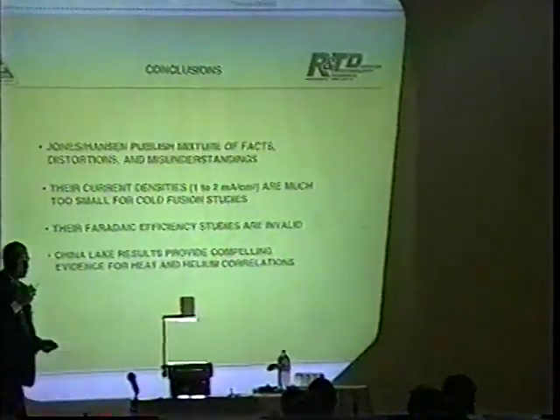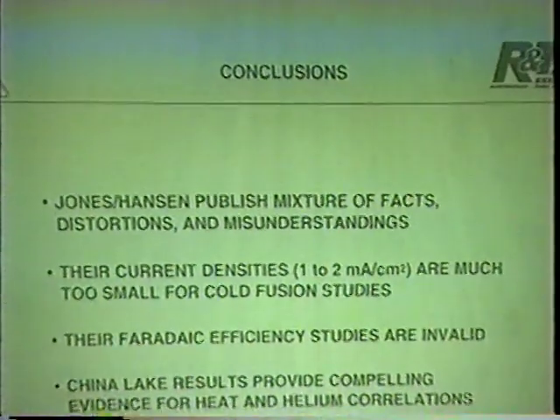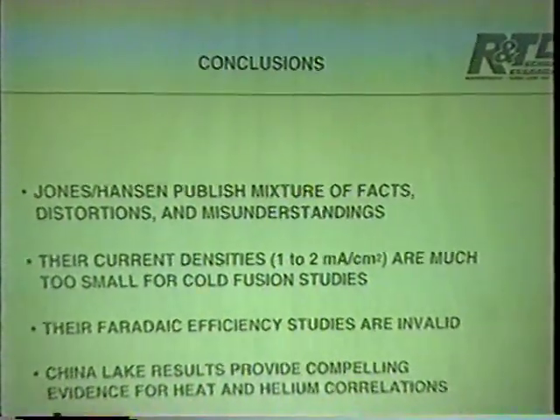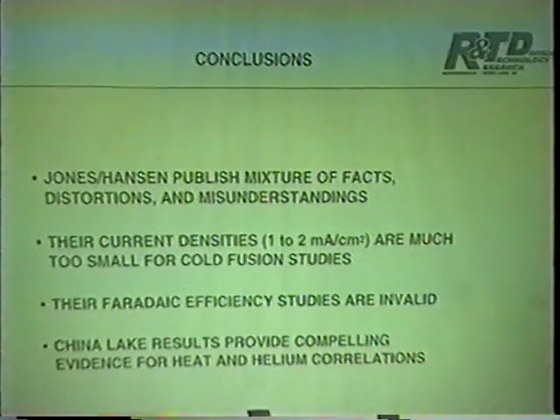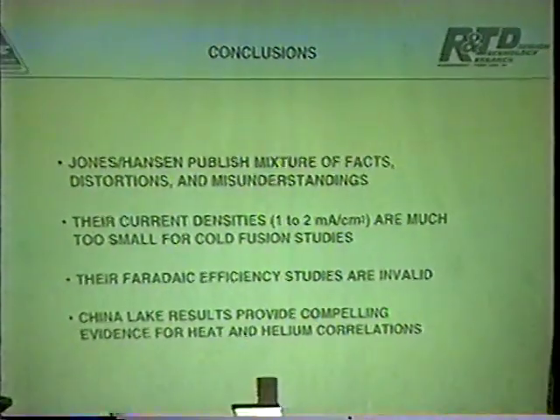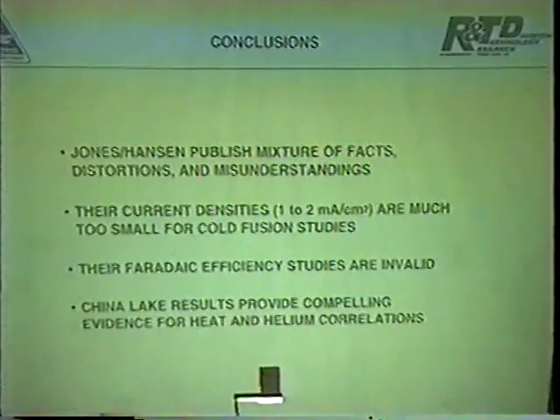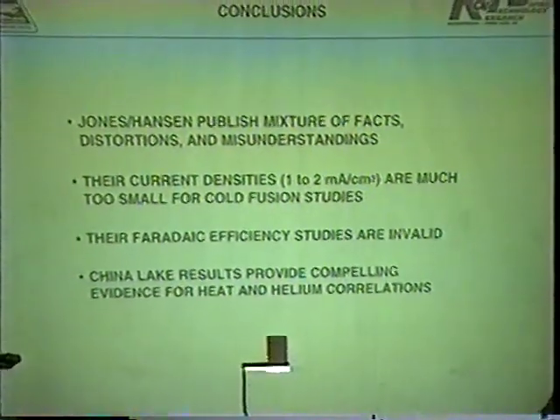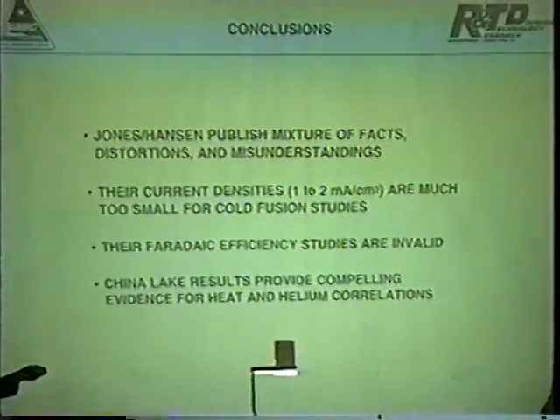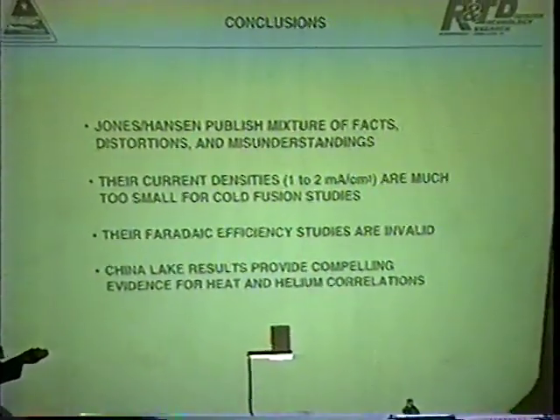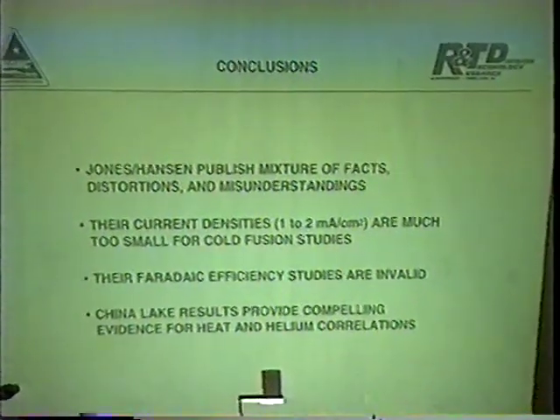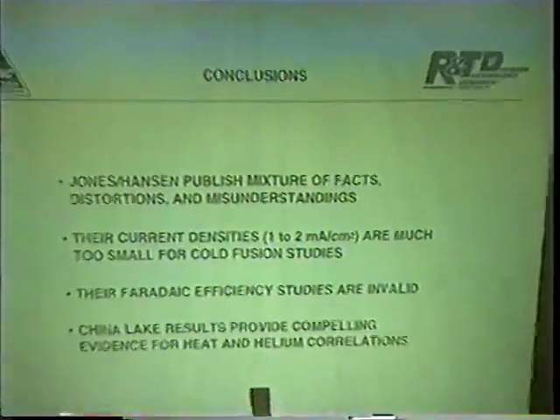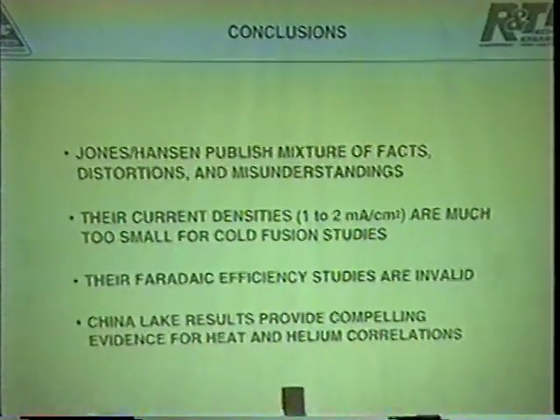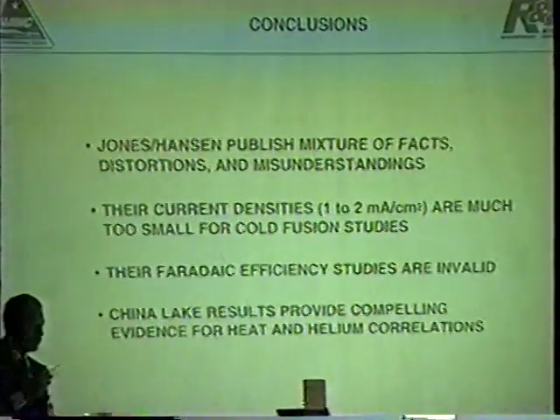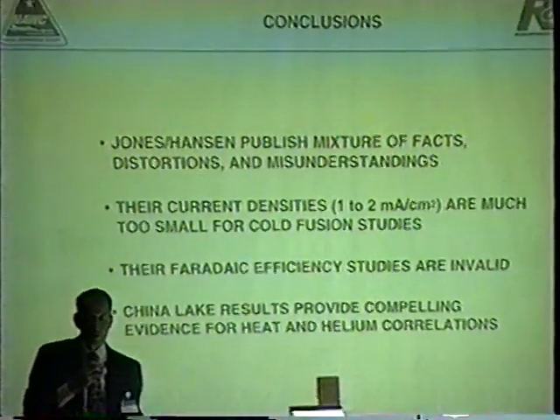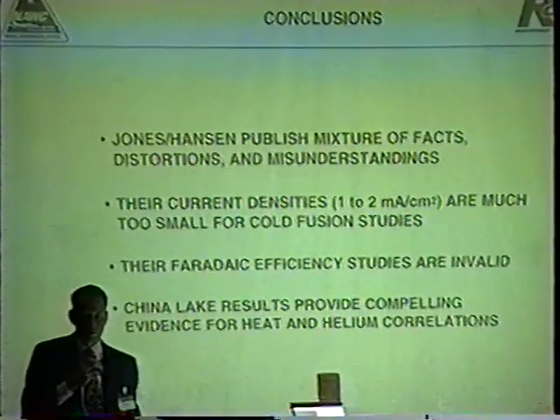And in my opinion then, Jones and Hansen published a mixture of facts. Some are facts, but a lot of it is distortion and misunderstandings. And in their look at recombination, they use current densities much too small, 1 to 2 milliamps per square centimeter. I don't know anybody that works down in that range. You need at least 100 milliamps per square centimeter. So their results do not apply to cold fusion studies. It's invalid, in other words. And I think our results provide compelling evidence that there is excess heat, and helium-4 is correlated with that excess heat. Thank you.